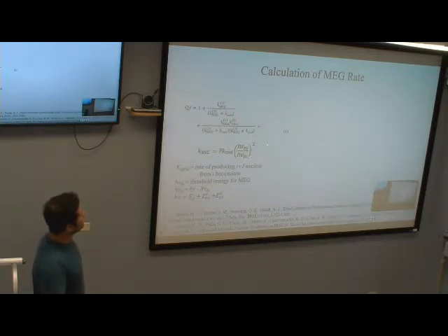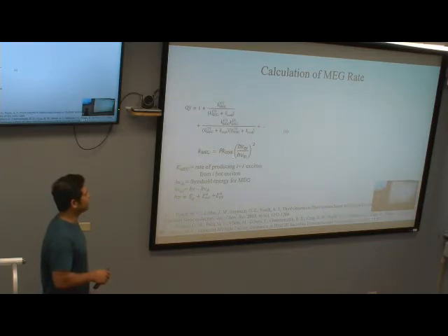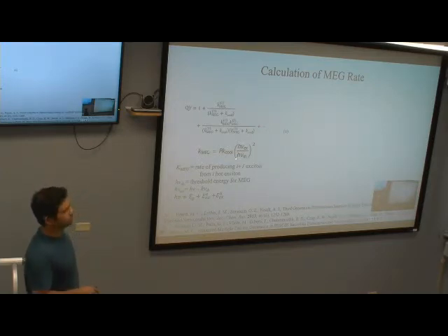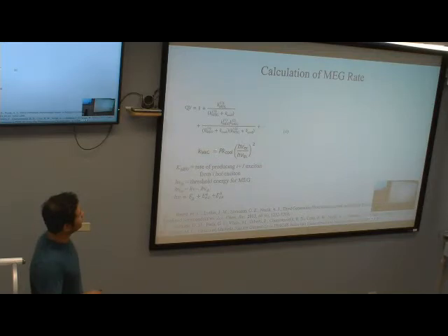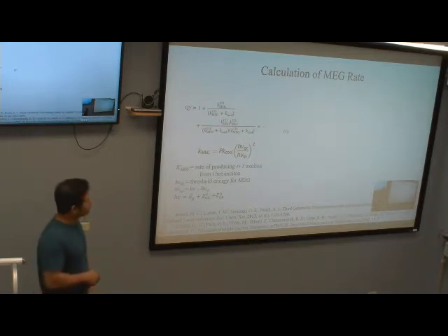They have another paper that derives this relation from the cooling rate and multi-exciton generation rate with the excitation energy by applying Fermi's golden rule, and the ratio, the competition between these two, can be characterized by another constant, P here. So from P, you can characterize how efficient your MEG is.